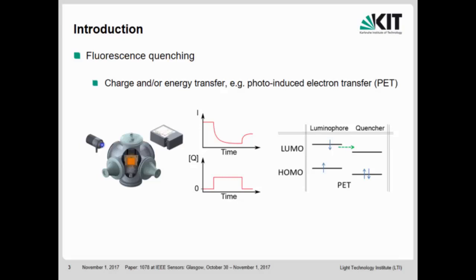And the physical principle that is underlying is a photo-induced electron transfer, which means what happens in these fluorescent dyes is, well, typically in organics you call this a HOMO and a LUMO level, which is comparable to the valence band and the conduction band in a semiconductor. So you excite the electron, and if the quencher is present, the electron can move to the LUMO level of the quencher and decay without any radiation. That's the reason why the fluorescence intensity will be decreased. And this technology offers potentially the advantage that it's ultra-sensitive and, well, you only need very few components, so you can make it very low cost and portable at the end of the day.